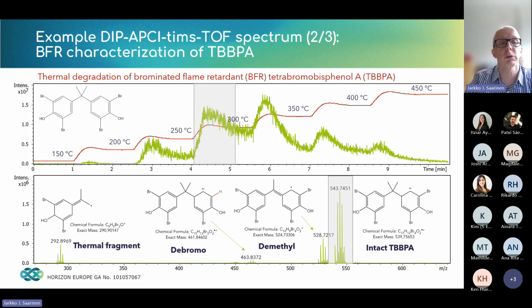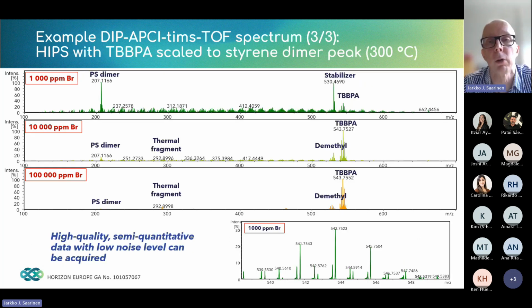And then we have also done samples in which we have a known amount of the TBBPA mixed together with, in this case, high impact polystyrene. So from 1,000 to 10,000 to 100,000 ppm of bromine content. And then typically, how we do the quantification in the mass spectrometry is that in the case of polystyrene, everything is interrelated to the PS dimer signal at 207, compared to the TBBPA signal at 543.